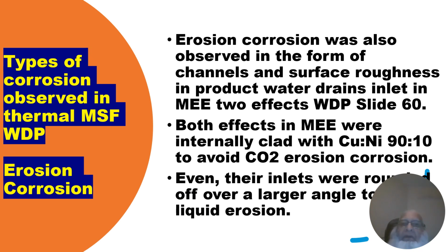Both effects in MEE were internally clad with copper nickel 90/10 to avoid CO2 erosion corrosion. Even their inlets were rounded off over a larger angle to avoid liquid erosion.